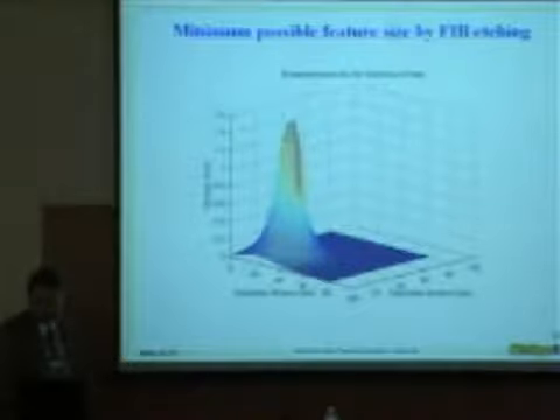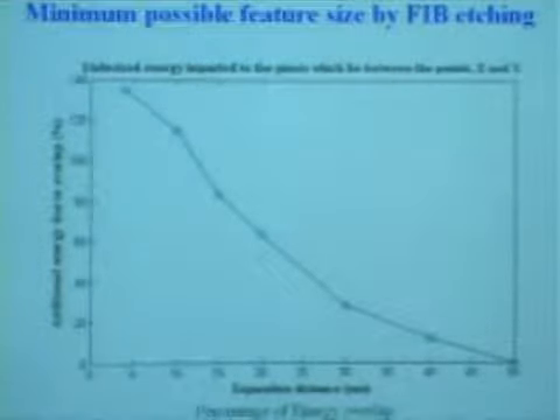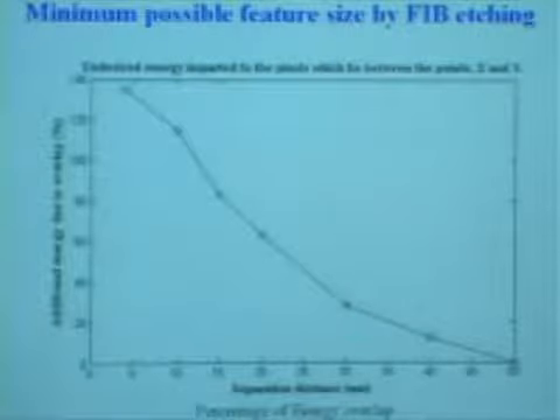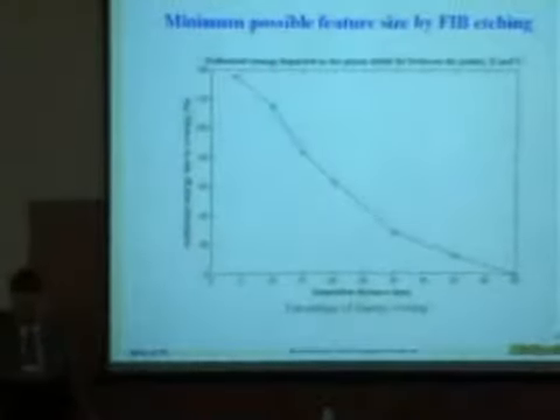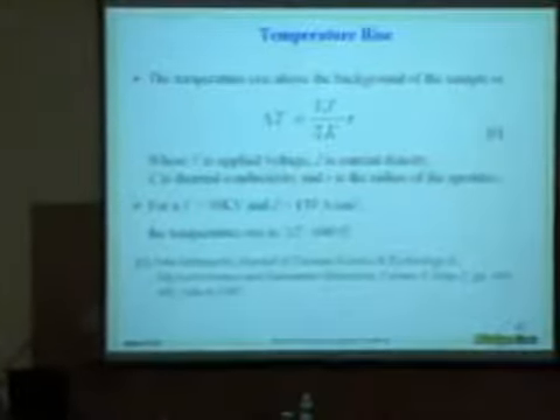And obviously as you get closer, that becomes even more of a problem, where basically you're overlaying your beam right on itself. And we see that we have really a functional limit in terms of how close in proximity we can produce features. And we've seen this through other experimental evidence that the amount of energy that's applied to the regions that we don't want to etch becomes significant at sizes below 30 nanometers, even for the smallest beam size that we can produce. We did some analysis of this based on the dose and the accelerating voltage and the radius of our raster scan, and we found that for, I believe, a 30 nanometer radius, we were seeing temperatures on the order of 600 degrees C locally where that dot was being produced.